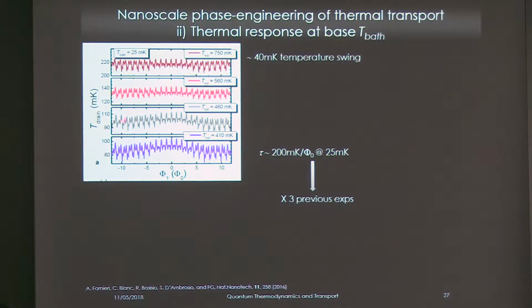So in the thermal case, by doing the same kind of experiment as before, it was possible to see that the electron temperature follows a complicated behavior, but basically mimics the electric one. So all these are beatings of the electron temperature simply as a function of the flux. Here we got a very nice 40 millikelvin temperature swing. So we doubled what we obtained in the first experiment.